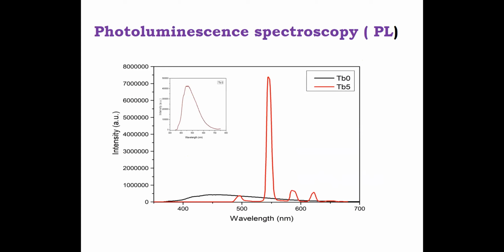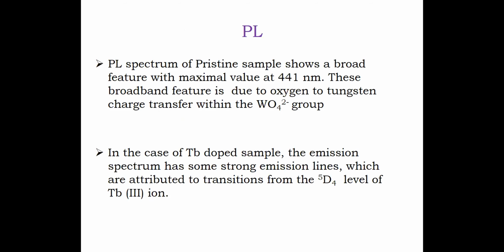So in order to understand more about the nature of the spectrum of terbium-0, it is enlarged and shown in the inset. PL spectra of the pure sample show a broad feature with a maximal value at 441 nanometer, which corresponds to oxygen to tungsten charge transfer transition within the WO4 2- group. And the doped sample spectrum has 4 strong emission lines, which are attributed to the transition from the 5D4 level of the terbium ion. The 4 emission peaks of terbium ions are observed at 496, 545, 587, and 622 nanometer, corresponding to 5D4 to 7FJ transitions respectively.